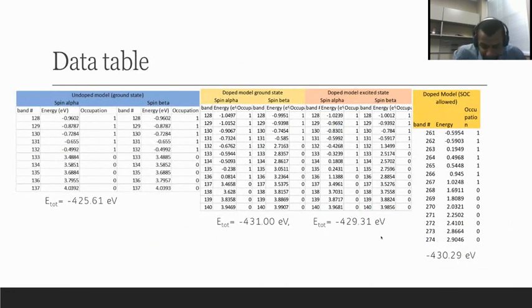So after these computations were done, the first thing that was obtained was the energies of the orbitals with the band numbers and the occupations for the undoped model, the doped model at the ground state, the doped model at the excited state, and also using the non-collinear spin DFT. In the first table, we can see that the band numbers and the energies look about the same for spin alpha and spin beta, and the occupations are also the same. So that would translate into a symmetric alpha and beta density of states.